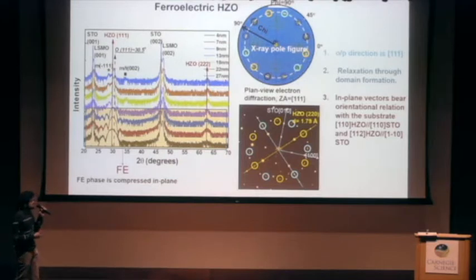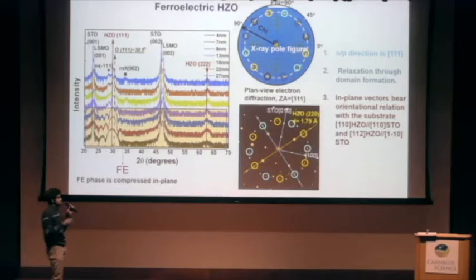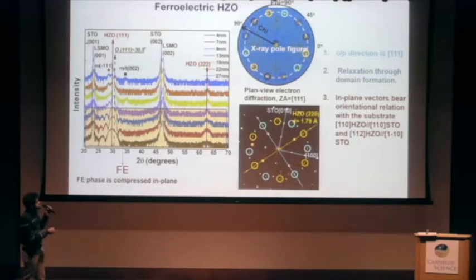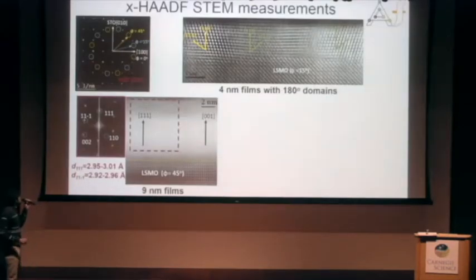Plan view TEM also says the exact same thing, TEM diffraction. So I circle the spots here in yellow, coming from 2 sets of domains, and in blue coming from two other sets of domains. And also we see a clear orientational relationship between the substrate and the film. Okay, so very quickly, because I don't have much time, we do also cross-sectional STEM measurements along several directions to get insights into what's happening.